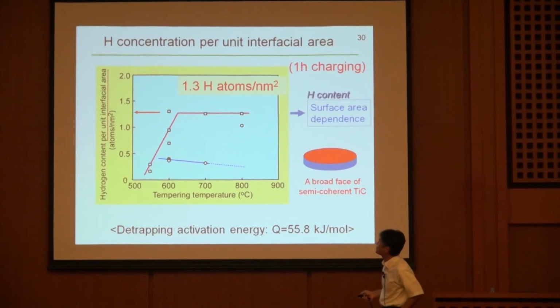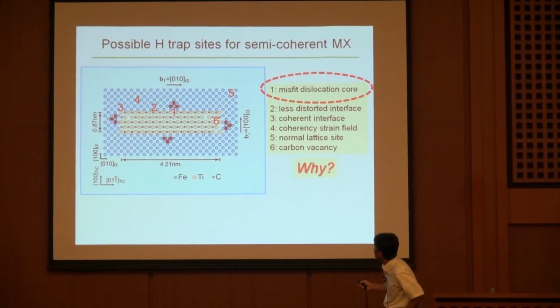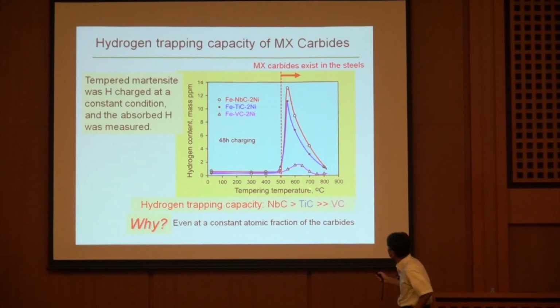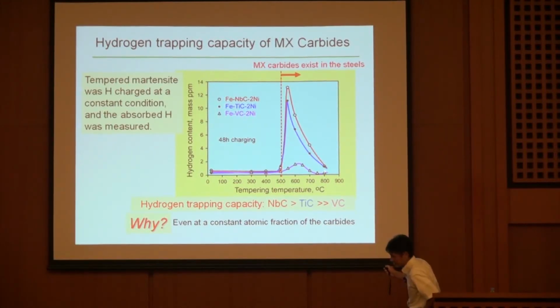Firstly, we checked the hydrogen concentration per unit interfacial area. Okay, you can see the unit, atoms per square nanometer. That shows the constant value of about 1.3 for the different tempering temperatures. Please look back at this data. So hydrogen content or hydrogen capacity decreases like this.